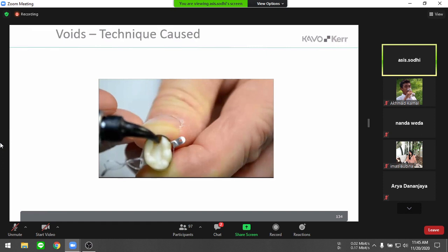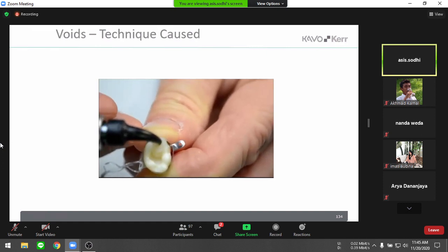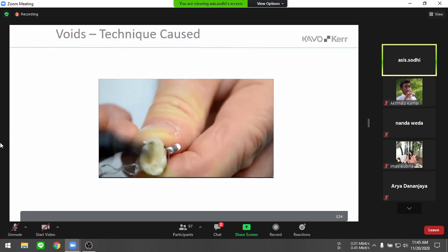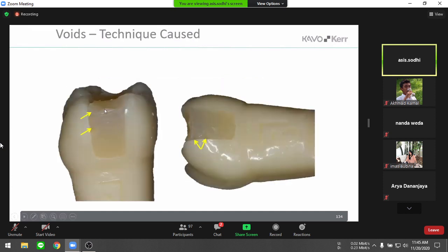So let's just see some of the technique errors that users can make. Okay, so the error here is that you did the procedure too fast, and because of that you incorporate voids. In order to avoid this, you need to ensure that you place the tip of the handpiece or the unidose tip at the bottom of the cavity here and slowly go up and towards the other end, and do not go back and forth because that can increase the chances of incorporating voids.